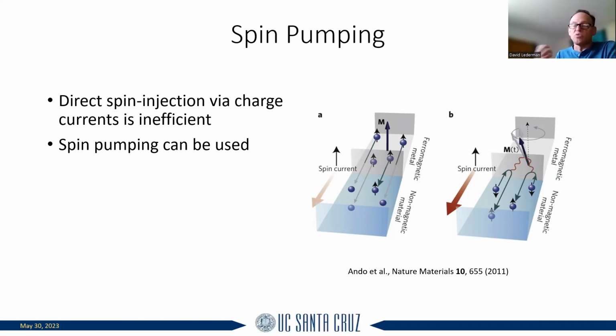For example, for a ferromagnet, it would be a microwave, and then you get these spins to start precessing about the applied field like this. Right at the interface between a ferromagnet and a non-magnetic material, this causes a spin current, because as this starts precessing, the precession actually decays as it goes in. But in order to do that, it needs to conserve angular momentum, and so it creates a spin current that flows in this direction. Okay, so that's a much more efficient way of doing this.